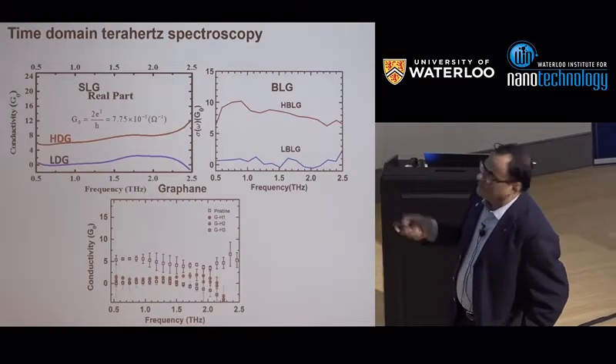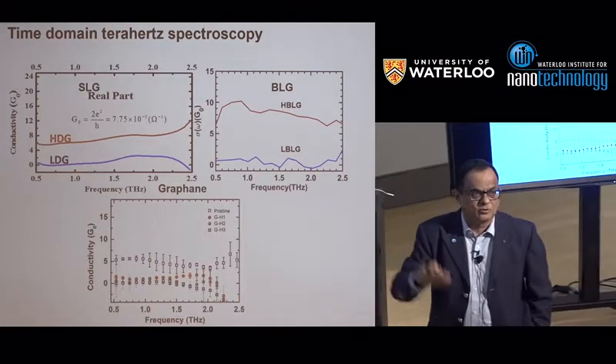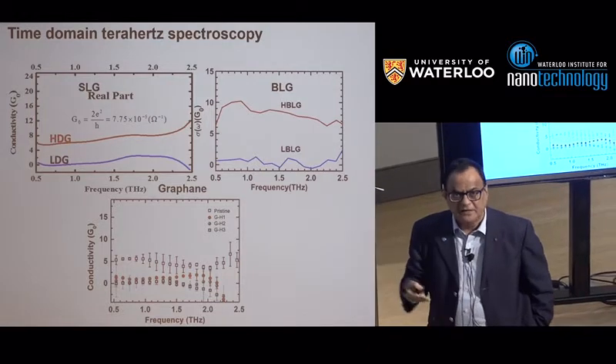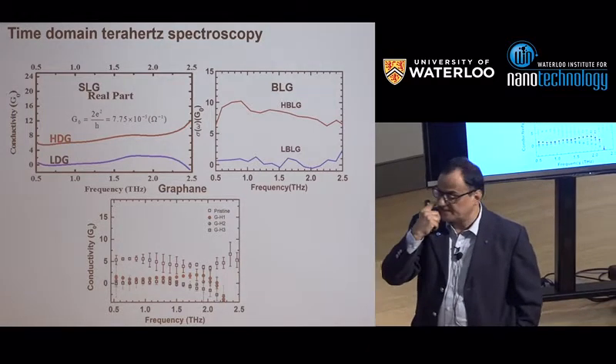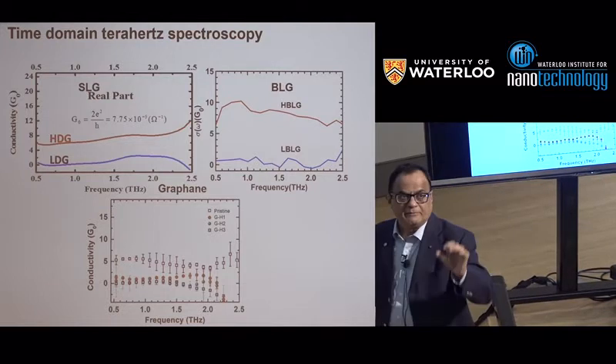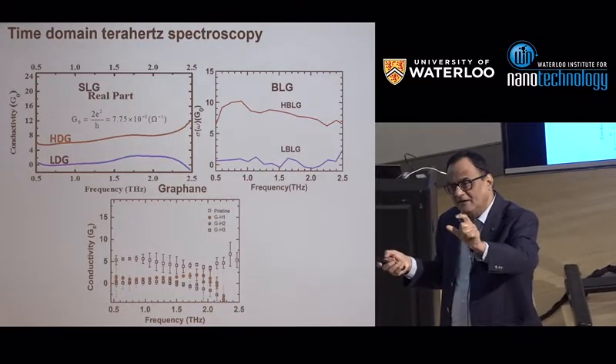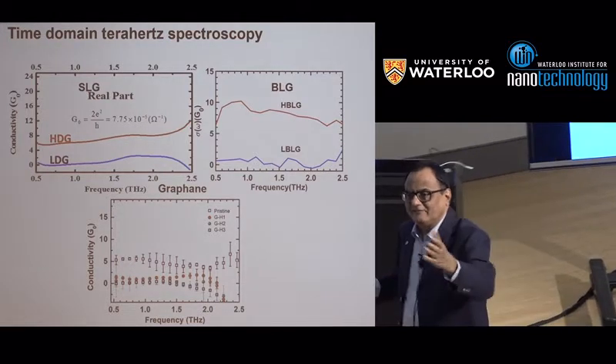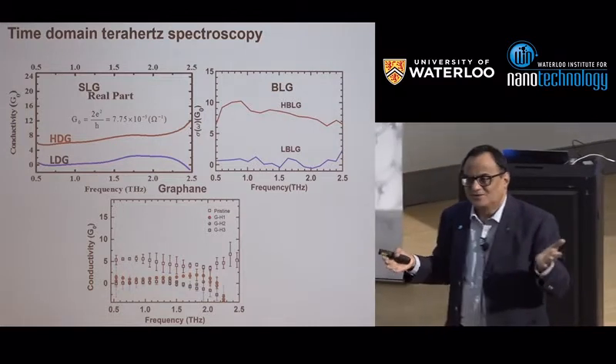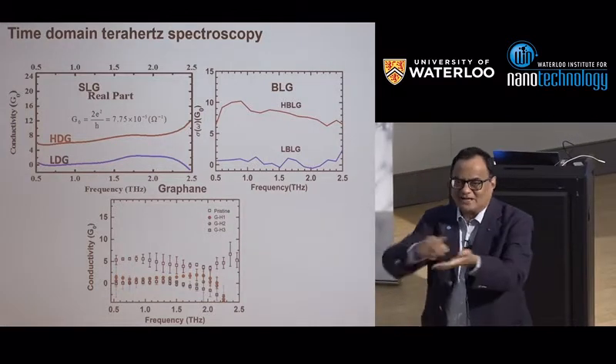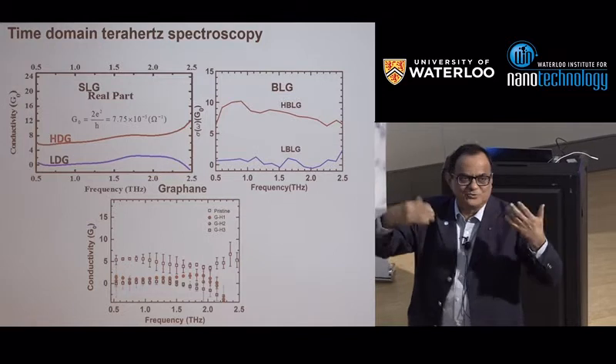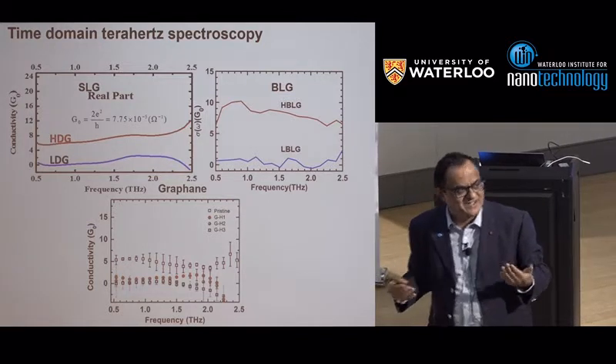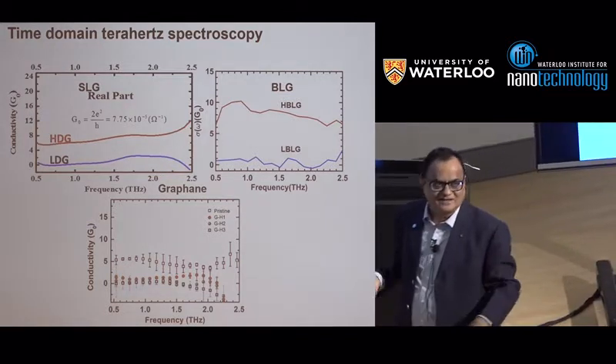So the first experiment you do is you grow your samples, mostly by CVD. These are all CVD samples because you need about 1 millimeter of the sample, because the terahertz radiation wavelength itself is 300 micron. So you cannot do it on a 5 micron exfoliated chip, which is what we used to do when we were making devices. Here CVD is the savior.